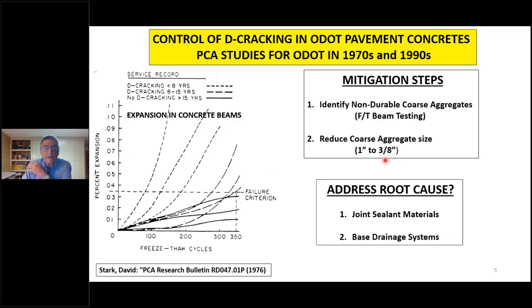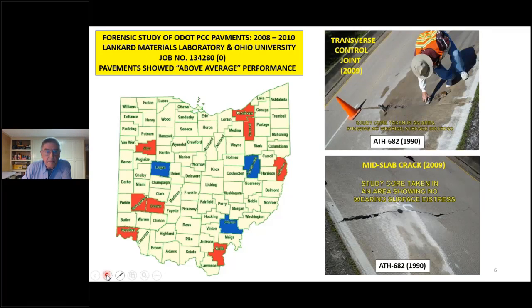One of the things that was done back then was to reduce the aggregate size from 1 inch down to 3/8 of an inch. And that really seemed to get a really good handle on the problem. That's been done since that time. I want to point out that the PCA workers did actually address the root cause, which of course is the water getting into the joints and through the joints. And so they looked at joint sealant materials and base drainage systems too. But at the time, ODOT thought that the D-cracking problem was pretty much in control with the reduction of the coarse aggregate size, and that has been the case. So not much was done about the joint sealing or base drainage since that time.